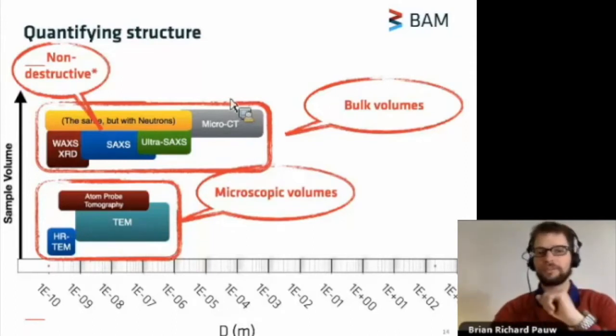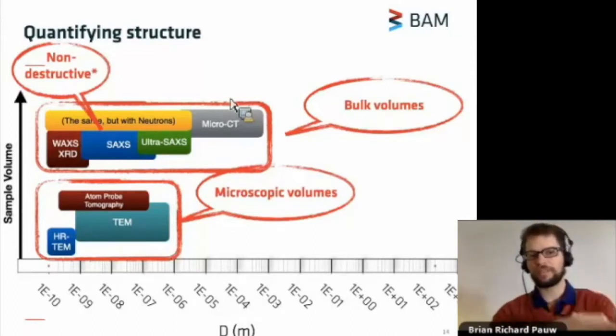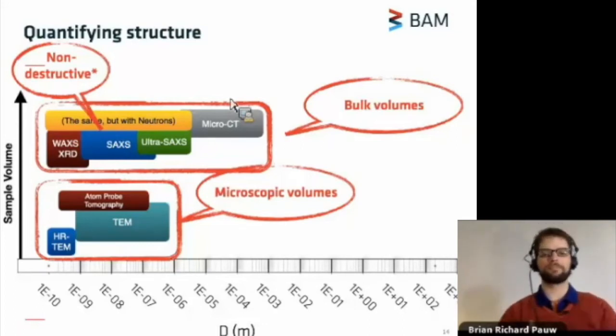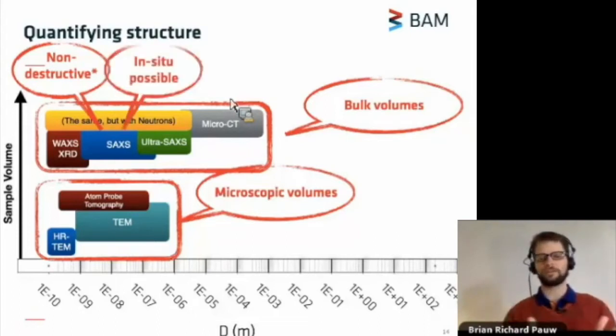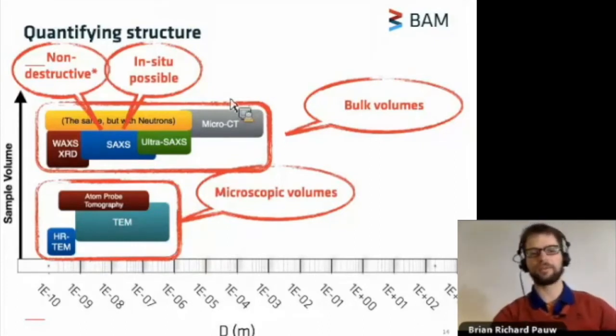But the non-destructive nature and the simple sample preparation that we can do mean that we can also do in situ experiments. And that means that we can take your sample pretty much as is, stick it in a machine, and expose it to an external field. And we can see how the structure is affected by that field. What do I mean with that?